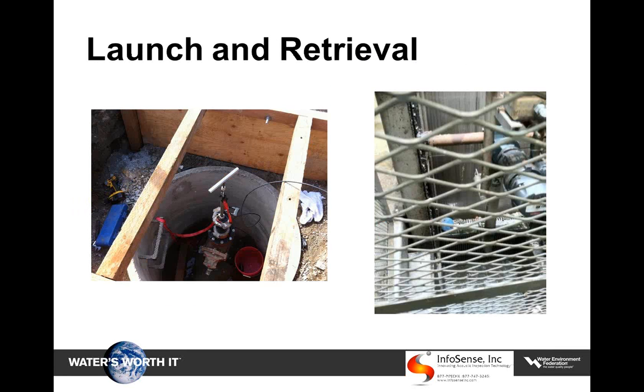So again, retrieval was fairly easy because we have a trash rack at the pump station, so when it exited the force main discharge structure into the pump station, it simply was retrieved on the trash rack. On the upstream end, we were able to launch the device through a valve that normally has an air relief valve on it. So we were able to simply close the blind flange, hook the launch device onto the blind flange, and they were able to launch the device very easily.